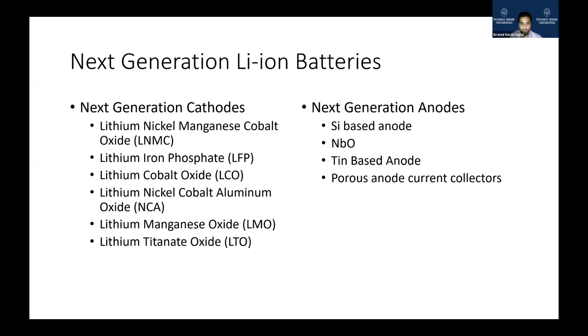As I showed you, when lithium goes inside this hexagonal structure, it actually takes a space. So when you put something inside the space, it expands, right? But graphite already has layers moving apart, a little bit far away from each other at nanometer scale. But silicon is not like that graphite, silicon has no moving part inside. So when we are inserting lithium inside this silicon, it is actually expanding. And how much is it expanding, can you imagine? This can expand 4 times. That means 400% expansion happens for this silicon based anode.